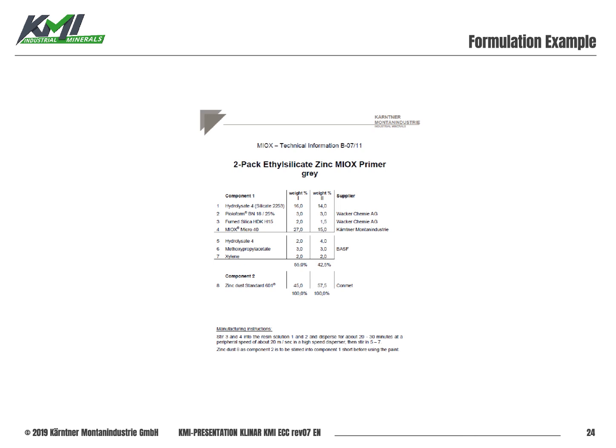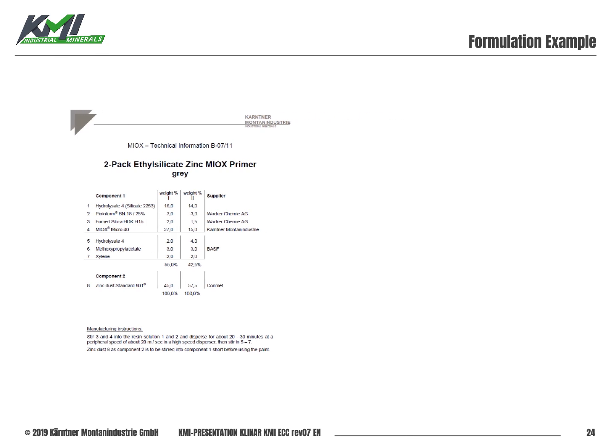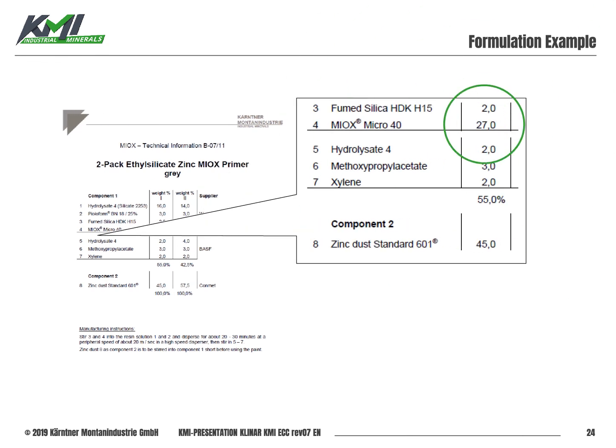Here you can see a typical base formulation. It's a 2K ethyl silicate zinc MIOX primer. And here you can see we have a replacement rate of roughly 30%. So we have 27% of Miox Micro 40 in the formulation and still 45% of zinc dust, which is a typical starting point.